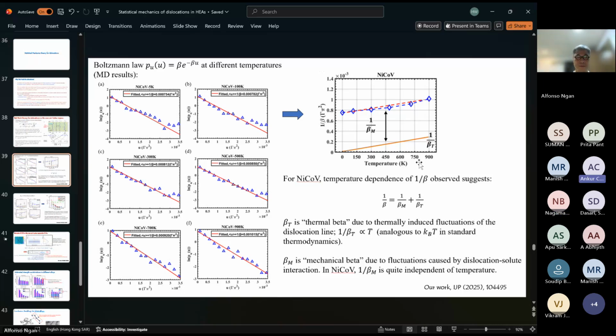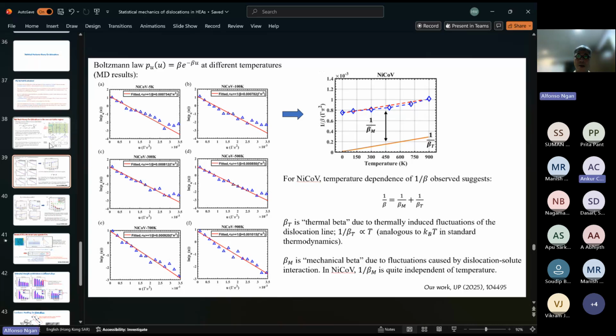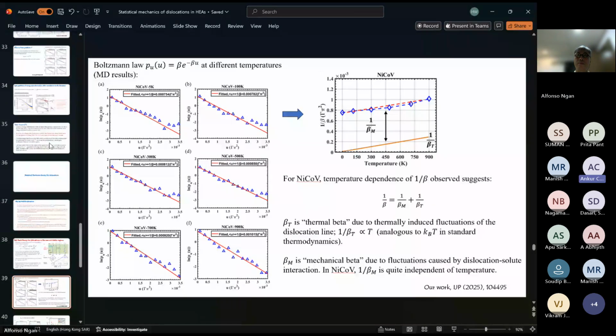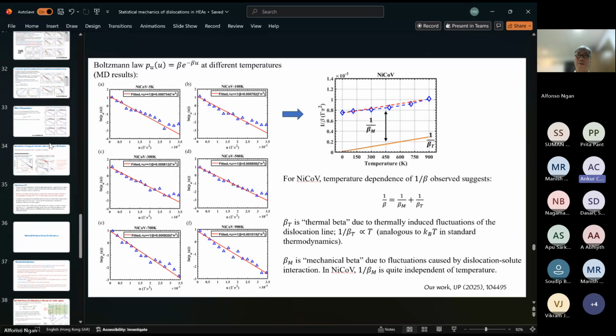Yeah, thank you very much for your nice talk. I just want to ask you with respect to the distortion we have because of the solute environment together with the stacking fault energy, for example. Can you comment on this, that if you have a perfect dislocation in the distortion and then a split dislocation with a stacking fault in a distortion, how would you comment on probably the effect on the stresses of the glide? Is there more difficulty for the partials with the stacking fault as compared to the glide?